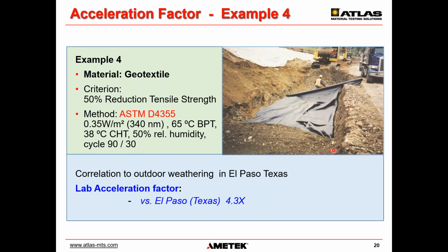Since these geotextile materials that you see here on the picture are usually dark, they would be close to the black panel temperature and in a dry climate probably not very sensitive to moisture. The fact that these materials are polyolefin-based polymers also means they are relatively moisture insensitive. So in this case, the UV radiant energy dose is probably the major degradation factor, and this would be consistent with the data. But the widely varying and sometimes surprising acceleration factors in some of the previous slides say there is something more to degradation and acceleration than just radiant energy. This may be due to temperature or moisture effects or even something else.